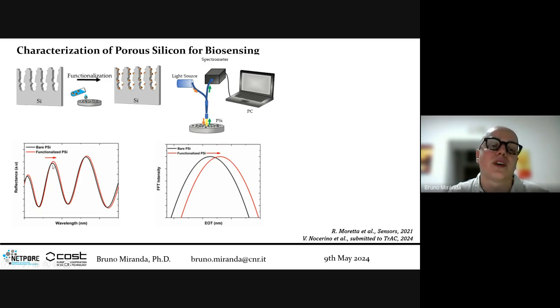What happens after functionalization is that you have a shift in the reflectance spectrum, and you can also compute a fast Fourier transform to be sure that what you see is coherent with all the fringes of this reflectance spectrum. So you perform a fast Fourier analysis, and you will have a single peak that is much shifted compared to the reflectance spectrum, and basically here you are making a more accurate measure of what is happening overall on your device.